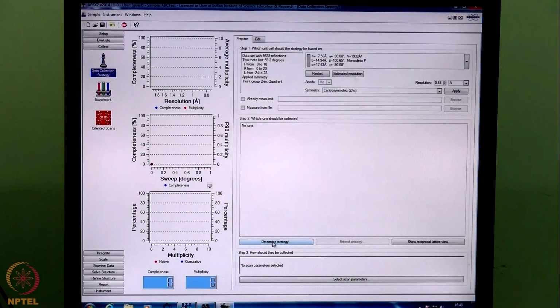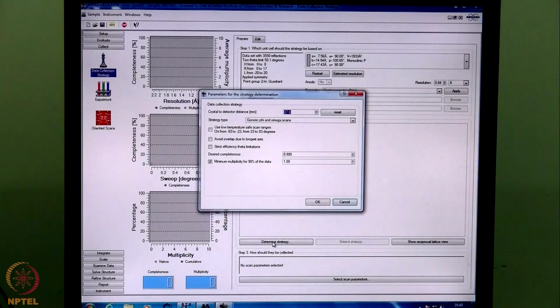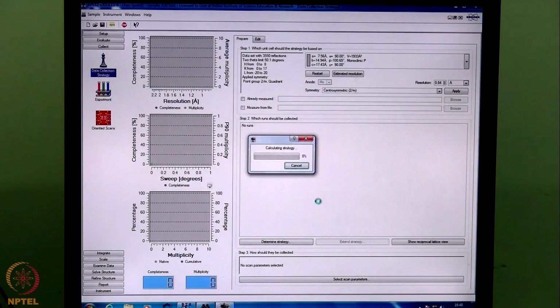So we click on determine strategy. It then asks us what is the detector distance at which we are going to collect the data. We can collect the data with 50 millimeter distance. We will use a generic phi and omega scan, and if we want to collect a room temperature data, then we don't need to do any required adjustments here, and we just say okay. It will then try to find out the best possible data collection strategy based on the orientation of the crystal and the unit cell that have been determined.